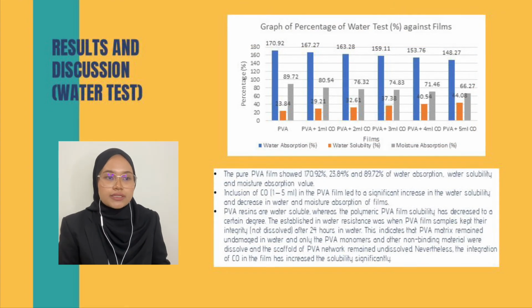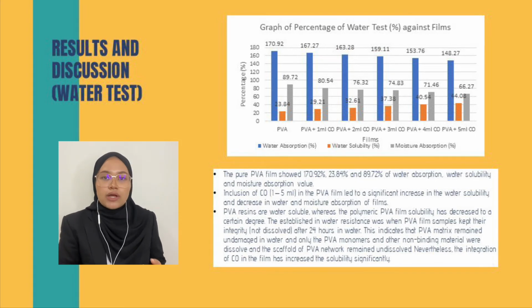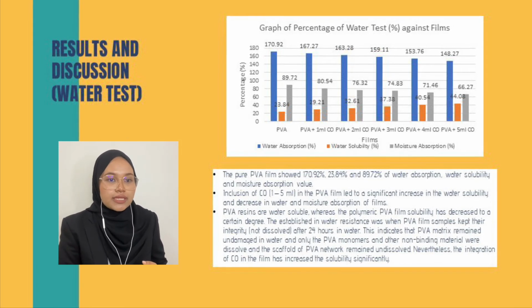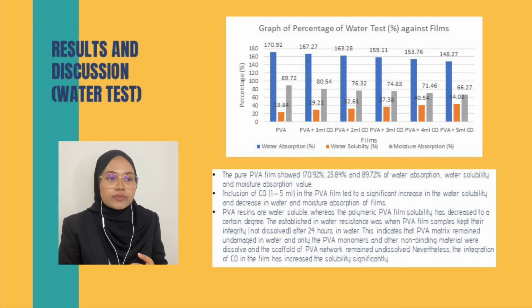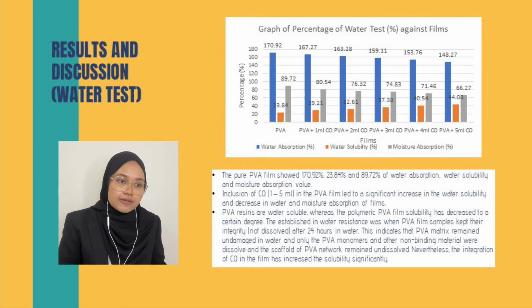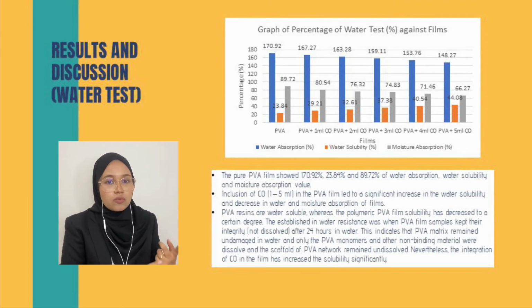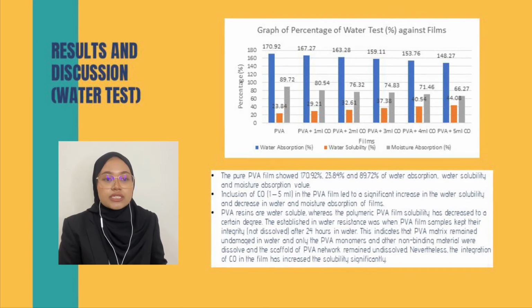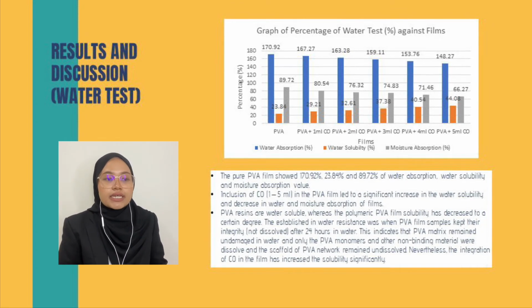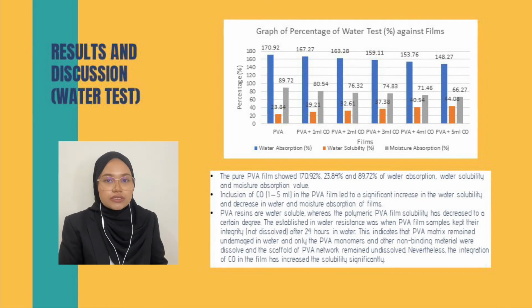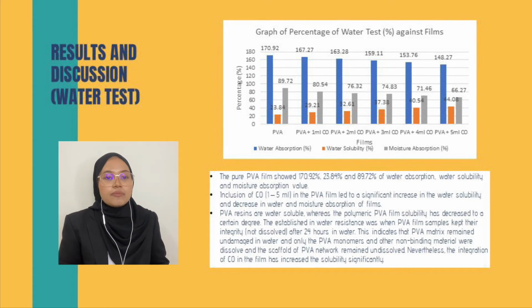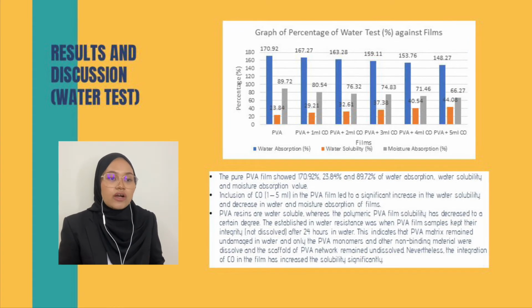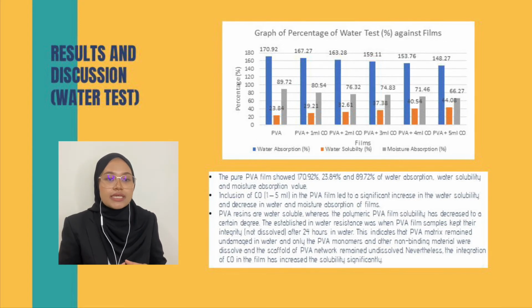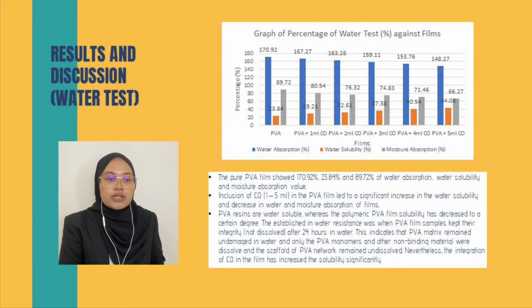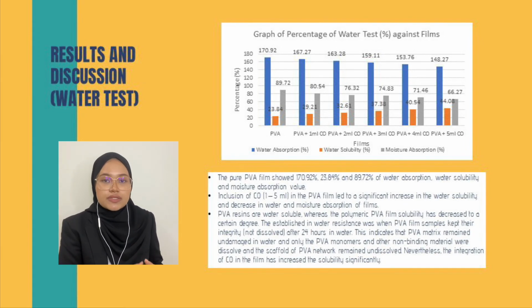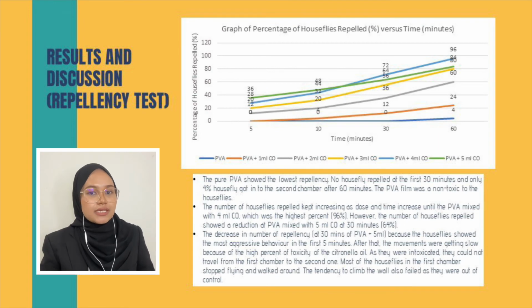Now we will go through the water test for the pure PVA film. It shows 170.92% for water absorption, 23.84% for water solubility, and 89.72% for moisture absorption. Inclusion of CO from 1 to 5 ml in the PVA film led to a significant increase in water solubility but a decrease in water and moisture absorption. Even though the water solubility increased, the PVA film samples kept their integrity, which is not dissolved after 24 hours in the water. This indicates that the PVA matrix remained undamaged and only PVA monomers and other non-binding material were dissolved.